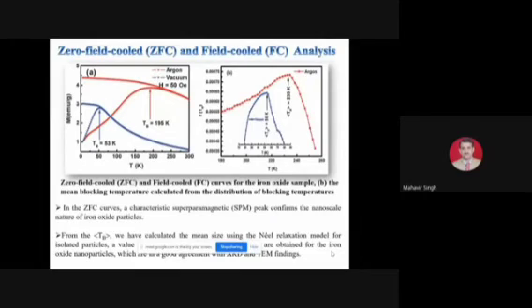So this is clear SQUID data. We have a clear high blocking temperature, which is suitable and close to 170 Kelvin. Next, please. So this is the theoretical calculation, AC susceptibility measurement, which we have put in theoretical modeling also. Next, please. So again, this is the gold coated magnetic nanoparticle. Next.